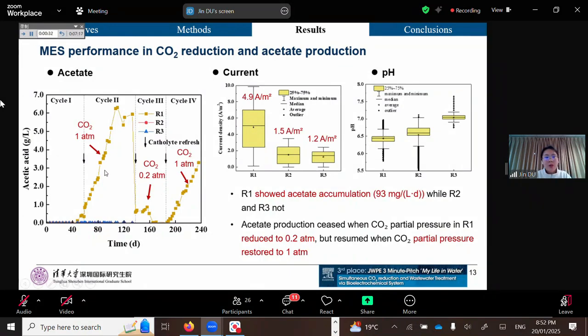Further, when the CO2 partial pressure of R1 was reduced to 0.2 atm, the acid production decreased and ceased. However, when the CO2 partial pressure was adjusted to 1 atm again, the acetate concentration resumed steady growth. These results indicated that the CO2-fixing bacteria in the MES system might prefer gaseous CO2, likely due to the higher affinity of bacterial membranes for gaseous CO2.